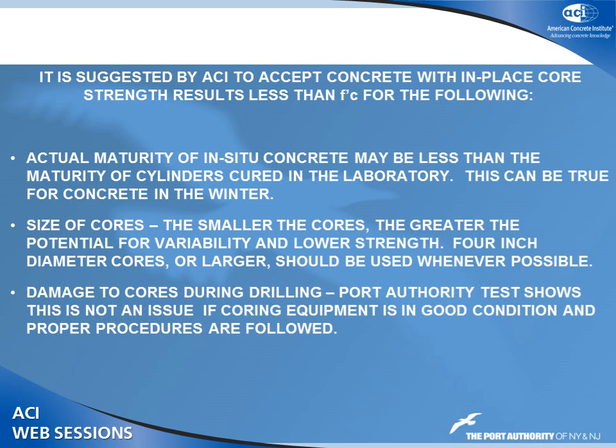Size of the cores, yes, that's certainly an issue. If you take small cores, you certainly build in a lot of variability. So if at all possible, we should use 4-inch cores. Damage to the cores, yeah, I guess there were papers written in the past where people found that there was damage to the cores, and they showed that it would certainly affect the strength of the concrete. I'm not debating that. The only thing that we questioned is, if we have 16,000 PSI concrete, how much damage are we really causing to the cores? And that's what we got into trying to figure out, what's really going on with these cores for high-strength concrete.